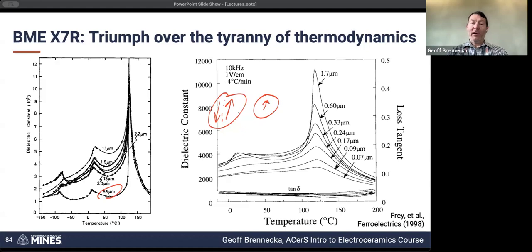So think about that. We are trying to make these materials as high permittivity as possible, and we need a thin layer, and we need that thin layer to have multiple different grains in it. So if we want multiple grains within 100 nanometers of a layer, each grain is going to be 10 to 20 nanometers. And the whole reason we're using barium titanate is because of this very, very high relative permittivity. But as we make those grains finer and finer to be able to fit into this 100 nanometer thick layer, the permittivity of each of those grains is now decreasing. So we have to fight harder and harder along the way.